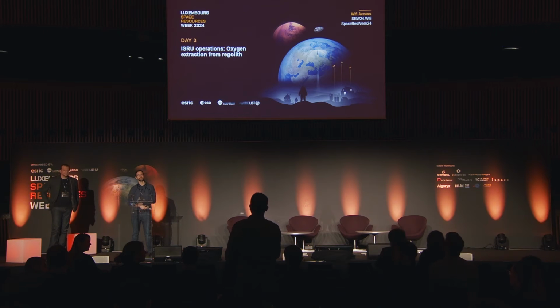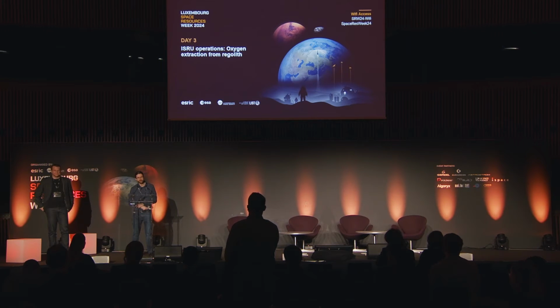What yield did you achieve so far with your eutectic fluoride salt mixture? What recovery of oxygen did you achieve so far? In some early experiments, we were at around 85%. This was an early installment of the process, and we can already see that there were some problems, for example, with material compatibility and some leaking in the system, so we hope that we can improve this further.